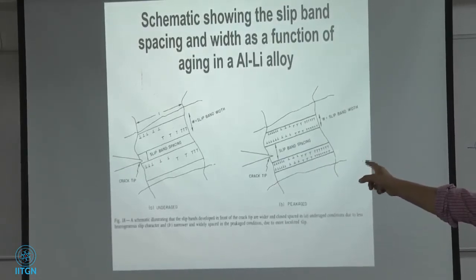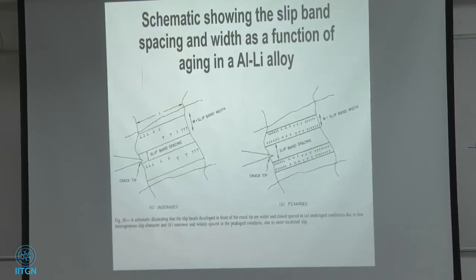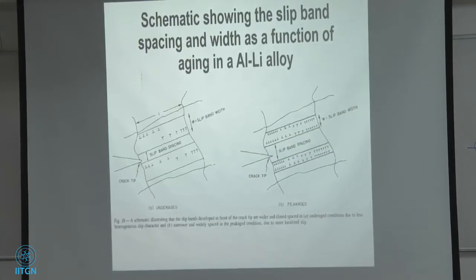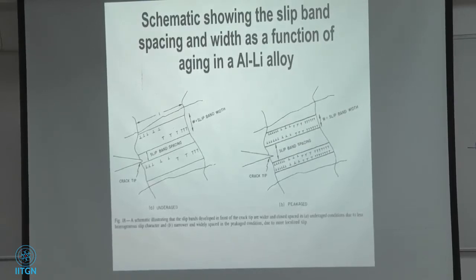Ready, Garu? Ready. So here is the slip bands, dislocations in slip bands. For the fracture toughness model, okay, just a schematic. Wide slip bands and low slip band width and spacing for underaged. For peak aged, larger slip band spacing and narrower slip band width. Okay, oh, we did this? Oh, yeah, I wrote it yesterday.